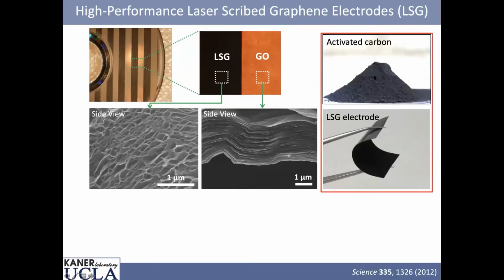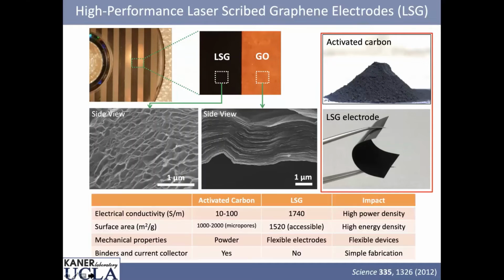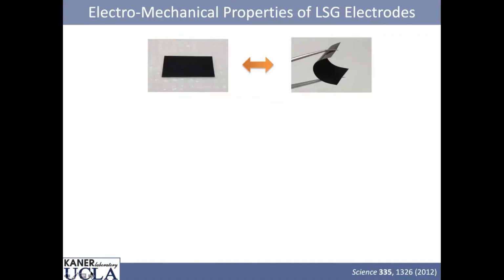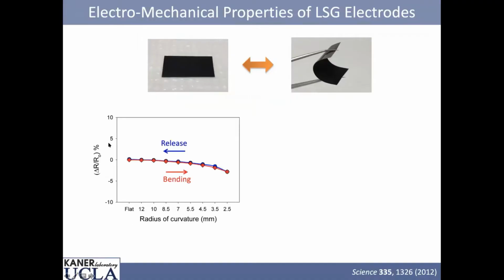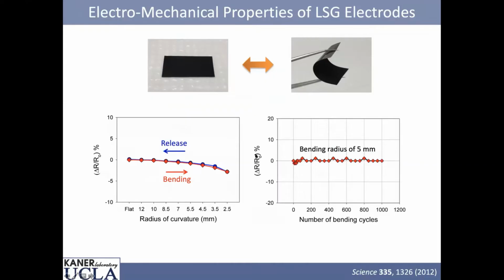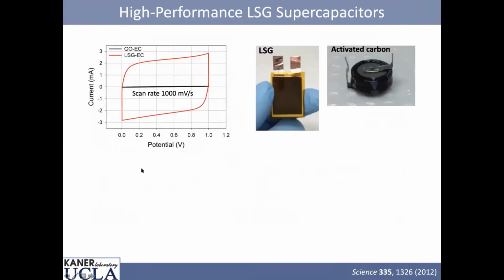All right, so here's activated carbon. That's what's used in current supercapacitors. Here's our laser scribe graphene. And I'll skip the things, but I'll show you it's completely flexible. So this is a change in resistance on bending, and you release it, it goes back. You can bend it 1,000 times, it doesn't care. You get the same resistance. So you can make flexible electronics.